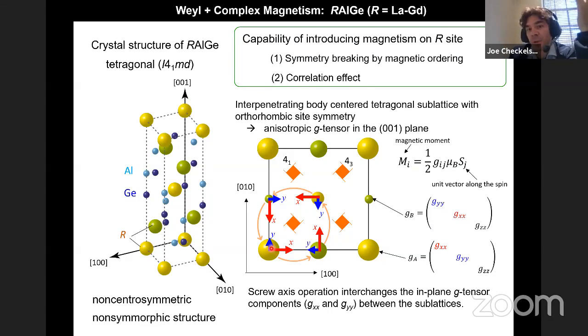And what it means is that when you do this 4-1 screw operation and you move from this position to this position, what you do fundamentally is rotate that local XY axis. And it means that basically, if you have some, for example, antiferromagnetic spin ordering between these 2 sites, even if the spins are antiferromagnetic, the moments will be ferrimagnetic, meaning the spin sizes can be